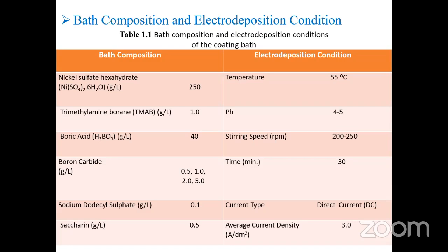In the plating bath, nickel sulfate hexahydrate is the main source of nickel ions, and trimethylamine borane (TMAB) is the main source of boron ions. Boric acid is the pH buffer of the bath solution, and it regulates the hydrogen ion concentration in the cathode film.